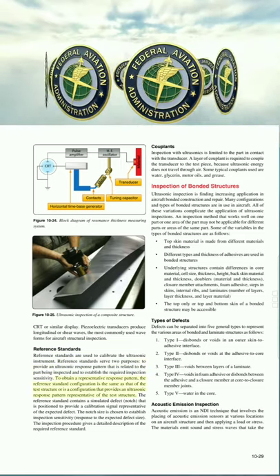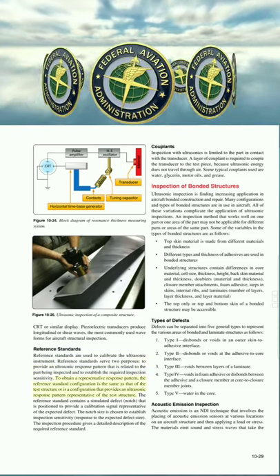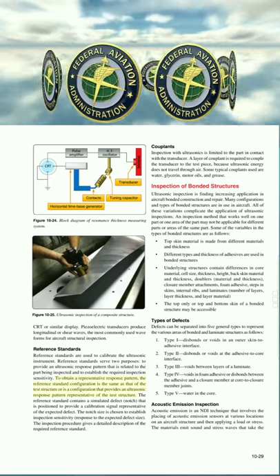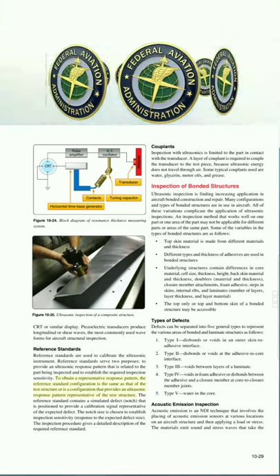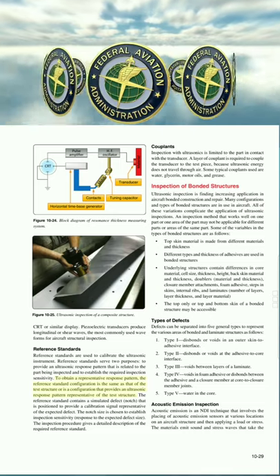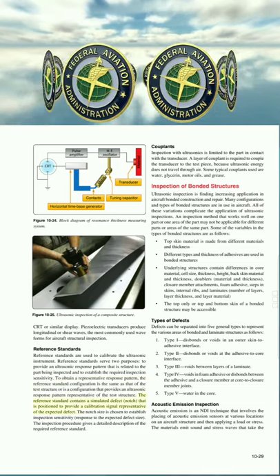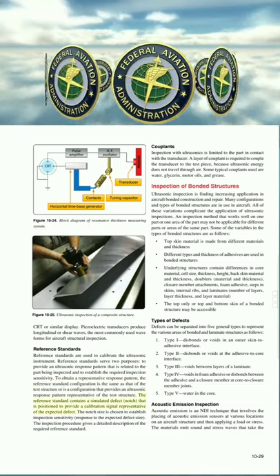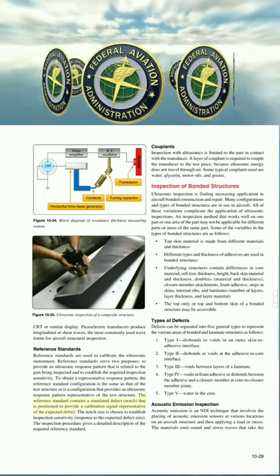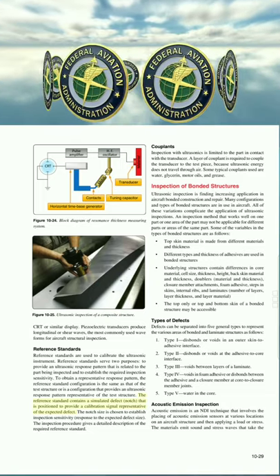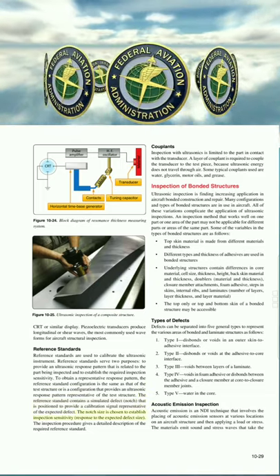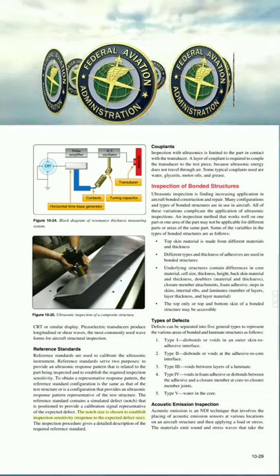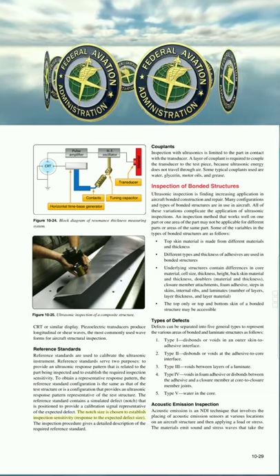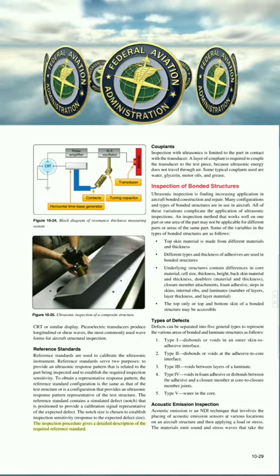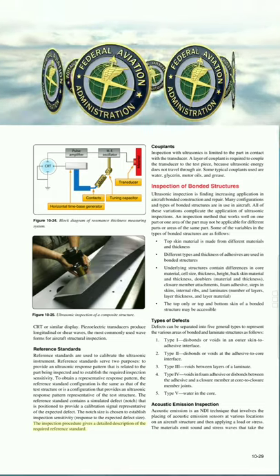To obtain a representative response pattern, the reference standard configuration is the same as that of the test structure, or is a configuration that provides an ultrasonic response pattern representative of the test structure. The reference standard contains a simulated defect notch that is positioned to provide a calibration signal representative of the expected defect. The notch size is chosen to establish inspection sensitivity, response to the expected defect size. The inspection procedure gives a detailed description of the required reference standard.